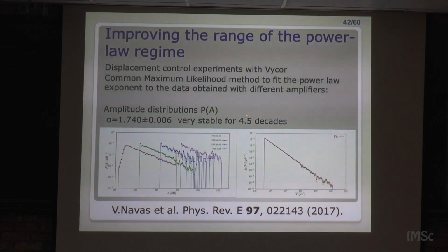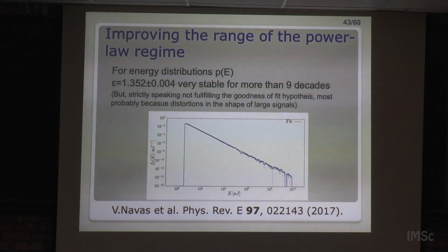You get this nice power law with 4.5 decades, but for energies, we get almost 9 decades of power law. The same that they get in earthquakes, almost. But, of course, earthquakes are there, here we are 30 decades below. But this, okay, this is what we got. And it's true that this exponent is, again, still not the same as earthquakes. So the 2 slopes, they don't fit so far.